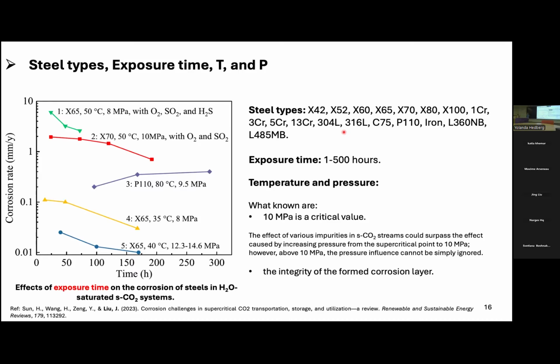As you could tell, the message I imply is that although lots of work has been done in the CO2-rich phase, different groups are working on their own studies. They may soak the sample in an autoclave for 10 hours and report their data. The other group may soak it for 100 hours, then report their data. So they are not comparable, and it's also hard for researchers or new students to follow. That also echoes my earlier comment that we don't have an ASTM standard for us to follow in this area.